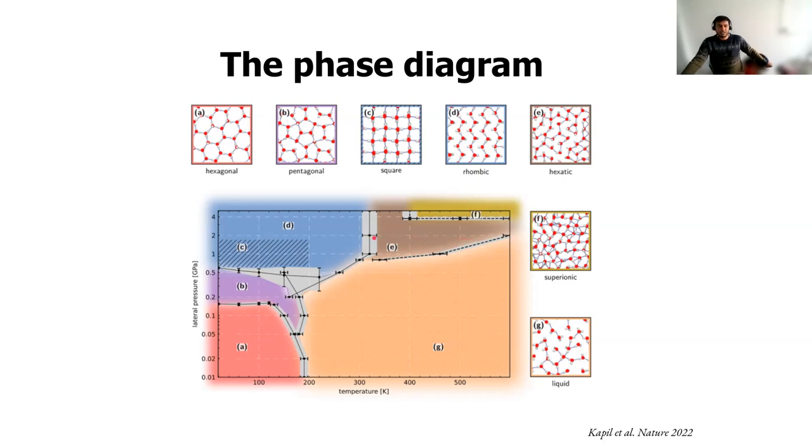And again, this is actually part of a much bigger theory here, which is the KTHNY theory in 2D physics, which dictates that any short range potential in 2D will undergo a two-step melting mechanism where either of the steps can be continuous phase transitions. And in this case, we find for our quasi-2D system, we have a first order solid to liquid and a second order, first order solid to hexatic and a second order hexatic to liquid phase transition.